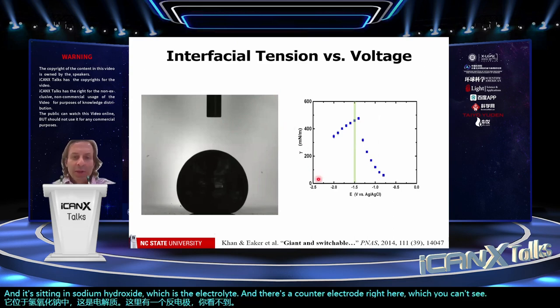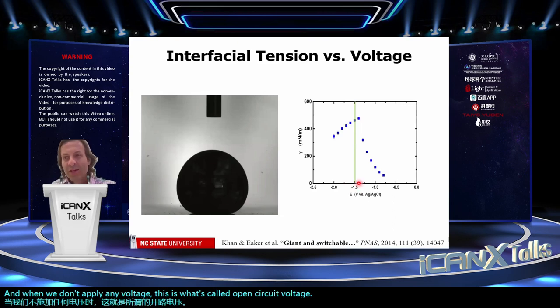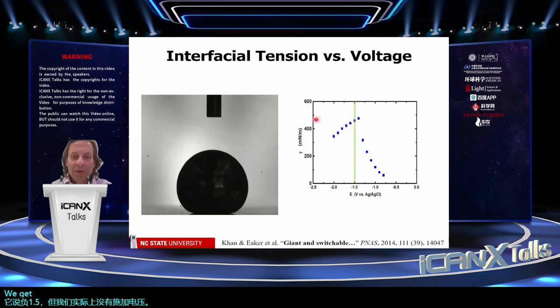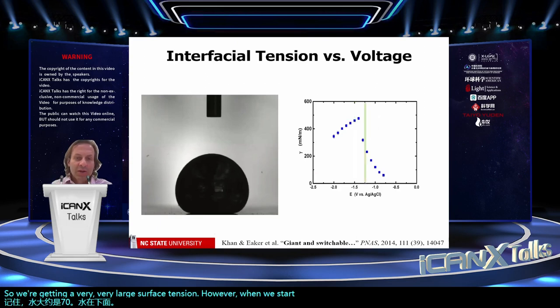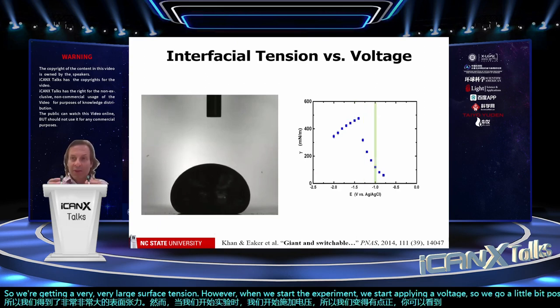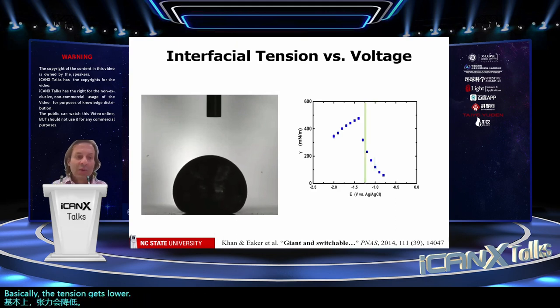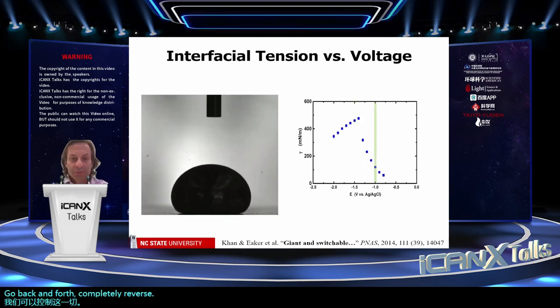And when we don't apply any voltage, this is what's called open circuit voltage. It says negative 1.5, but we're actually not applying voltage. We get a very large surface tension, almost 500. Remember, water is like 70. Water is down here. So we're getting a very, very large surface tension. However, when we start the experiment, we start applying a voltage. So we go a little bit positive. You can see the droplet starts squishing. Basically the tension gets lower, and we can control this, go back and forth, completely reversible.